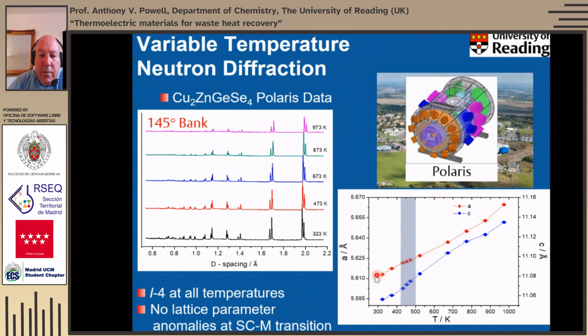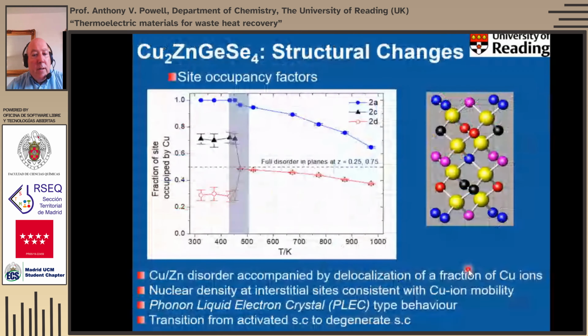And if we actually do the Rietveld refinement, we find that when we get through this region, this gray stripe showing the region where those electronic anomalies are, we see no lattice parameter anomaly either. Now, fortunately, the PhD student who was doing this, whilst initially disappointed, decided to look at this in a bit more detail. And what he found is, if we look at the site occupancy factors, initially we have this disorder between the copper and the zinc sites. So it's not a 50-50. It's a slight preference for the copper in one site, the 2c site, over the other site, the 2d site. And then there's copper that fully occupies this 2a site.